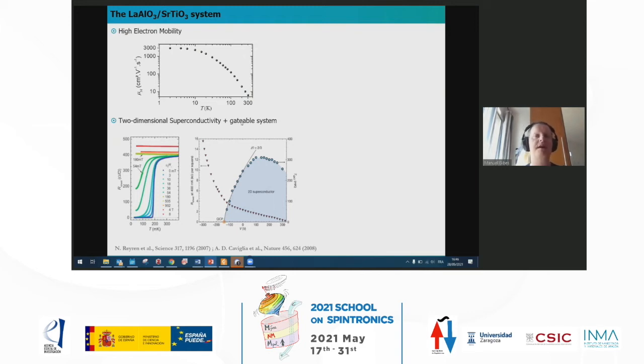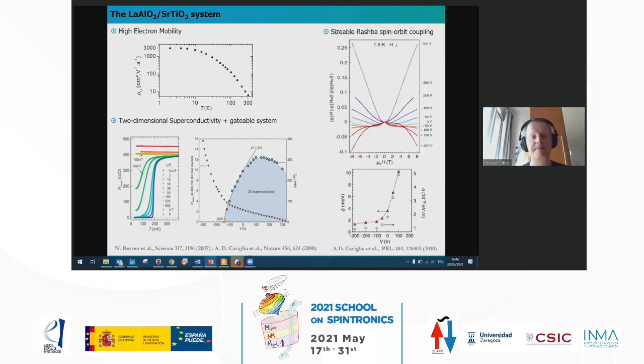So if you apply a backgate, you can accumulate and deplete carriers with a large efficiency. And this does a lot of things to the 2DEG. Basically, you can turn superconductivity on and off by applying a gate. You see here that here you have superconductivity, and then you can kill it if you apply a negative gate voltage beyond here, minus 150 volts, for instance.